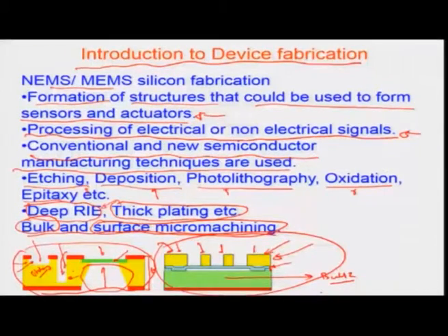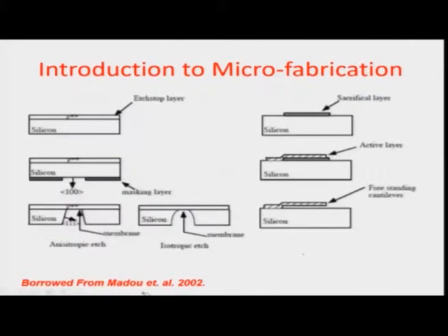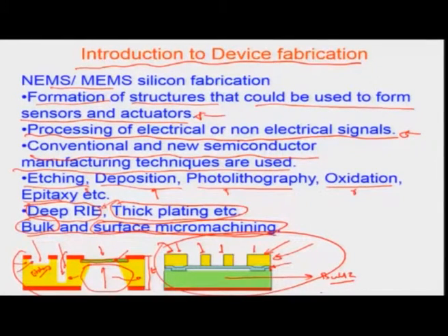And this structure right here is the structure which is again etched out from the silicon, and this meets the green surface right about here and proceeds no further, because the etching being carried out stops wherever there is this P double plus layer. So, this is a process called an etch selectivity driven process, so that you can obtain a very thin film, a small film, on the surface of this particular silicon wafer.